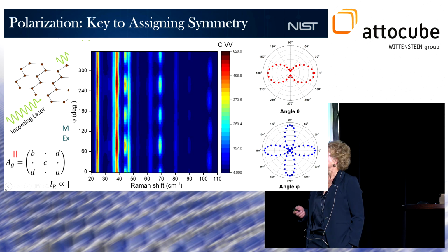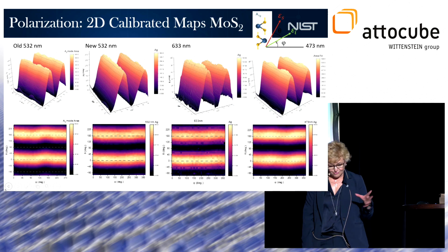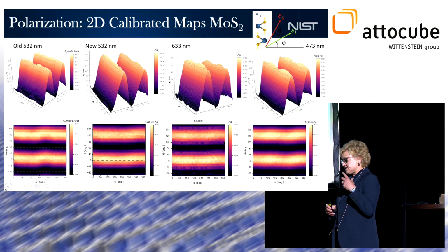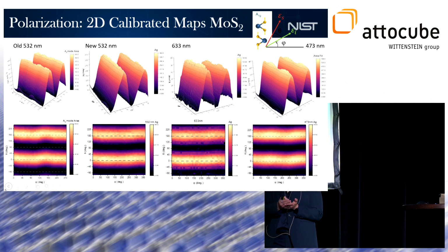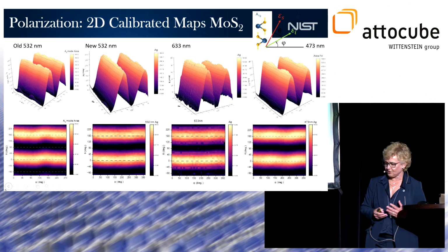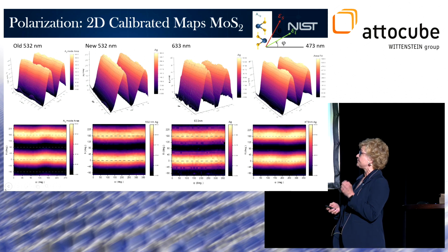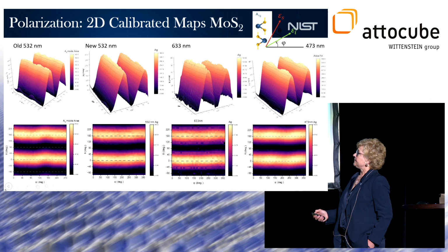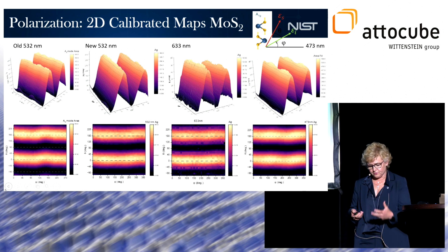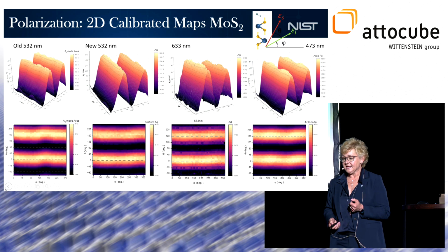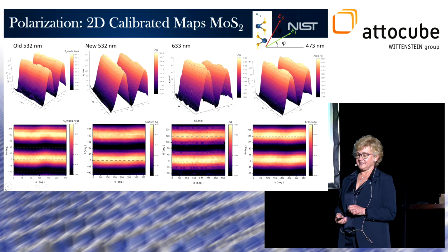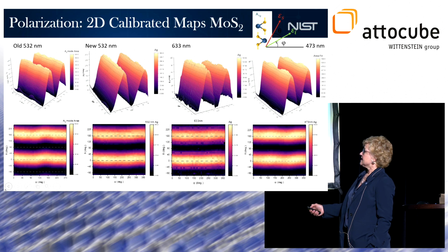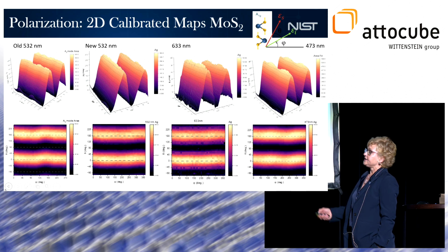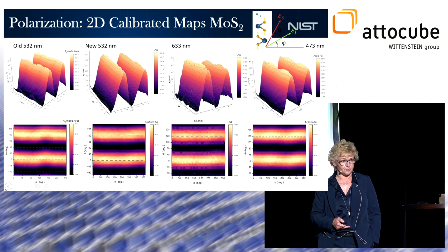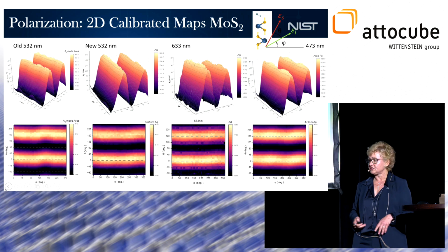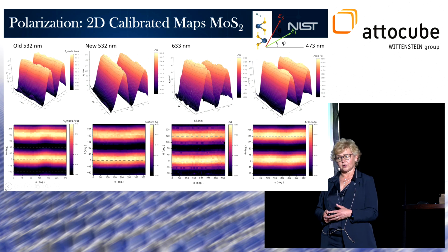But it is a nuisance to do good polarization. I'm just throwing that out there because it's an interesting phenomenon of how easy you think polarization should be, versus how challenging it actually is if you want to do it well. As it turns out, I work at NIST, and we do a lot with industry when they have measurement challenges. They were trying to do some polarization measurements at a semiconductor plant. And so we actually devised a way to use moly disulfide as the calibrant for polarization measurements. And so now there is a protocol for how to do that.